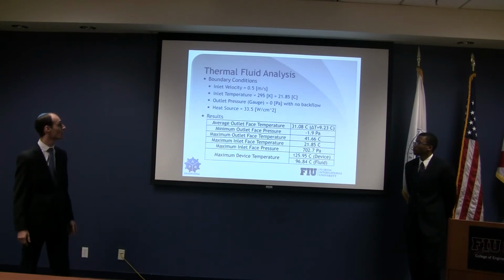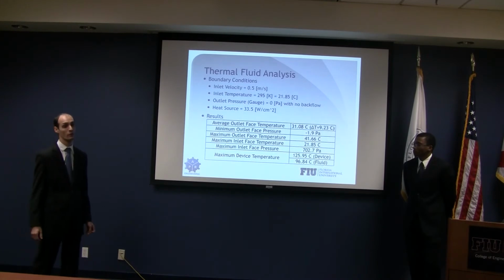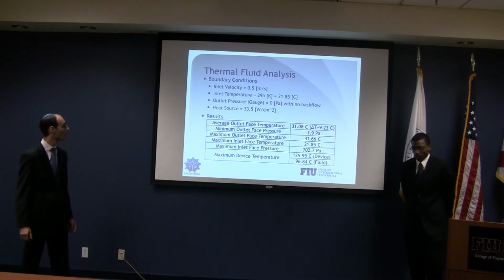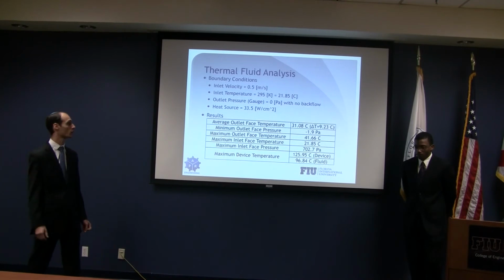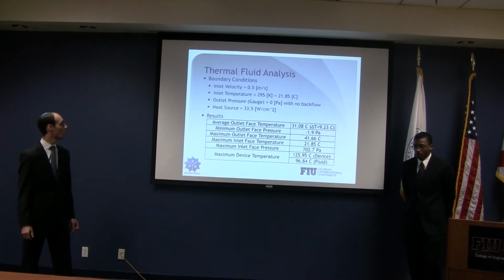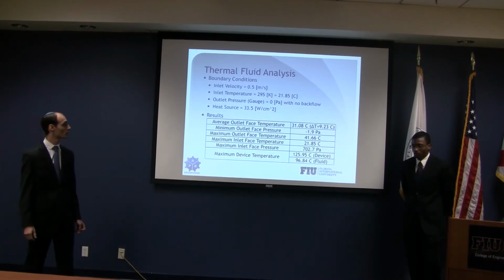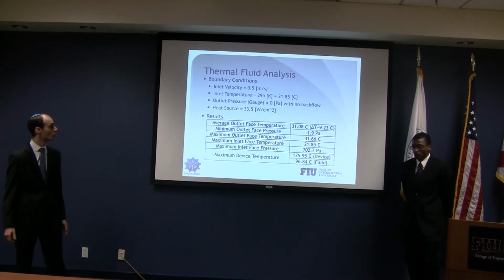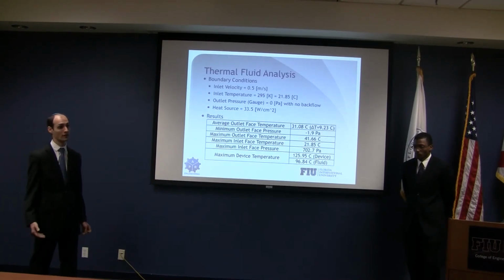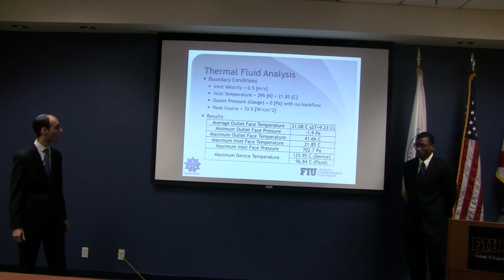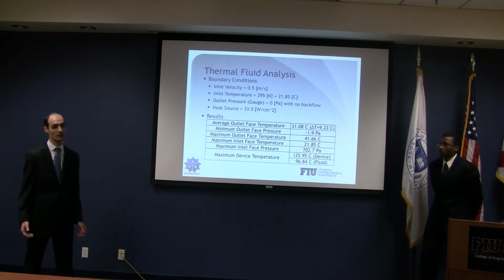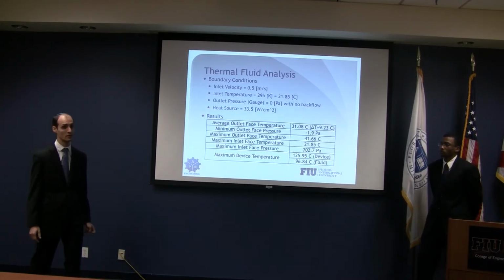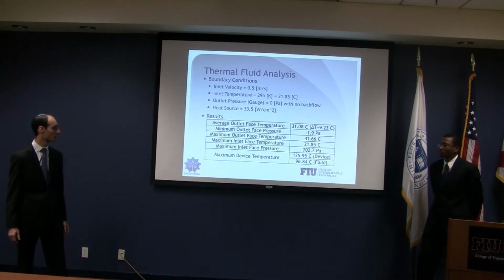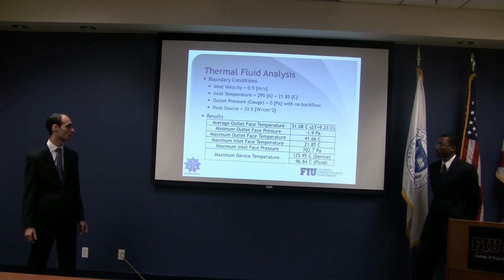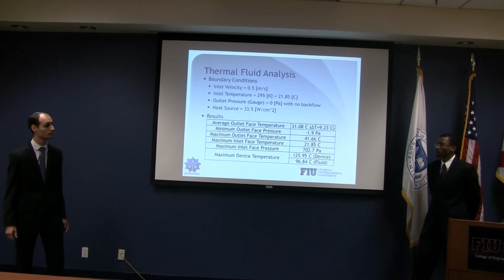On this, we'll have a heat source of 33.5 watts per centimeter squared, and an inlet temperature of 21.85 degrees Celsius, inlet velocity of 0.5 meters per second, and no pressure with no backflow on the outlet. That's gauge pressure, not absolute. And that should give us a delta T around 9.23 degrees Celsius, and maximum temperature in the fluid of 96.84 C, which is below boiling, so we avoided that.